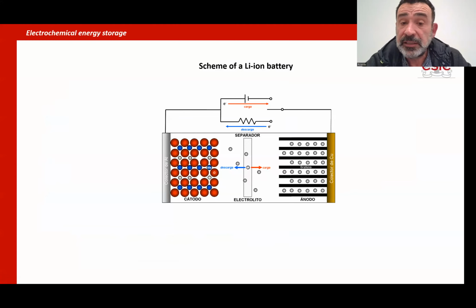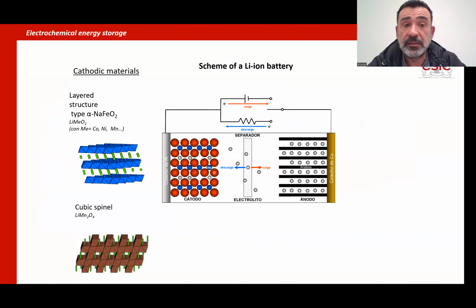And the key point in batteries is lithium-ion batteries, the ones we are using all the time. I want to show you the scheme of a lithium-ion battery and how it works. The material we use in the cathode is normally a lithium metal oxide. The most common one is lithium cobalt oxide. Cobalt is expensive, difficult to obtain, so we are trying to move to lithium manganese oxide. Other materials, lithium iron phosphate, for example, are also commercial. But you need, anyhow, one material that is able to keep lithium in the structure.